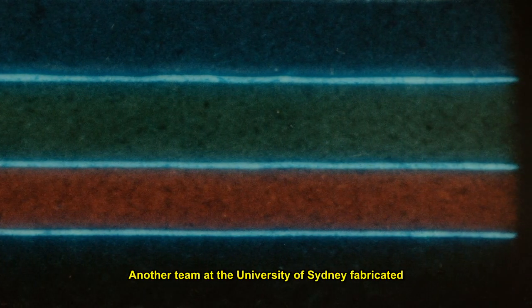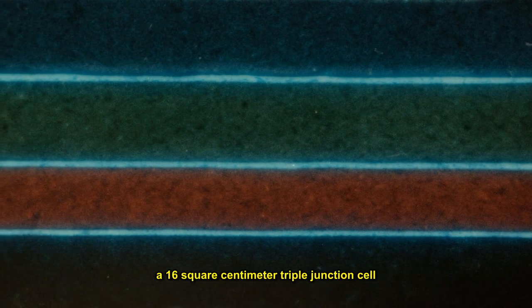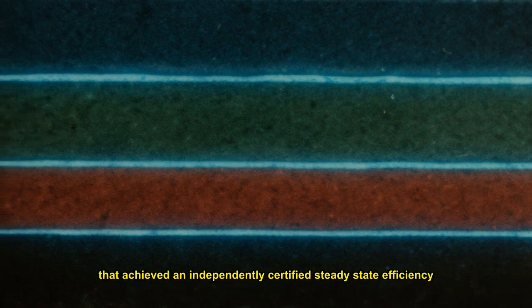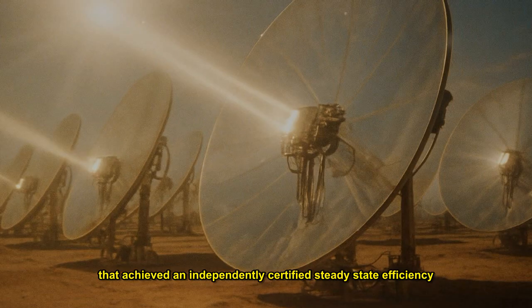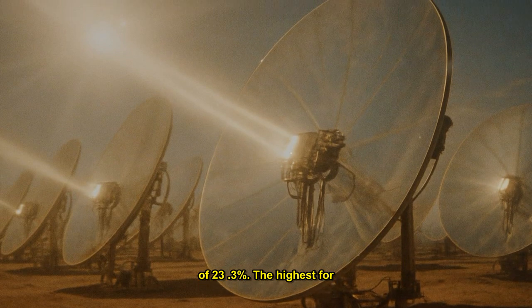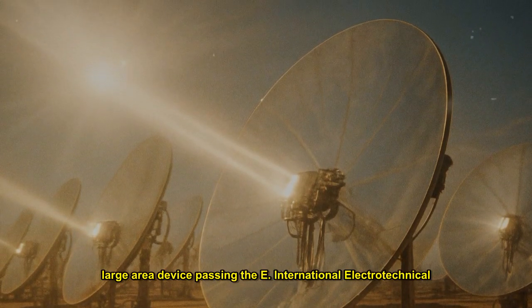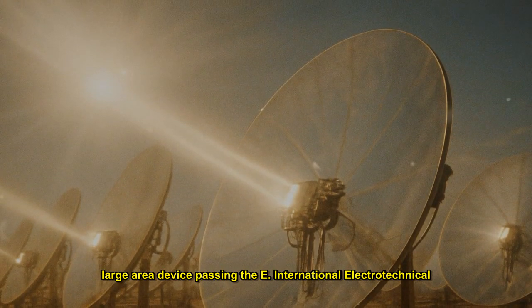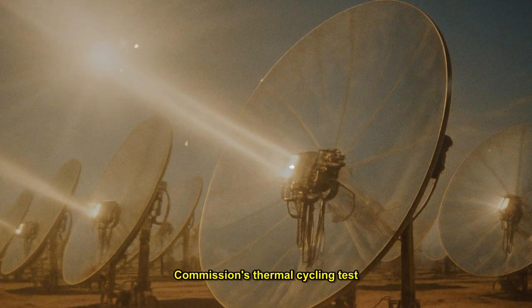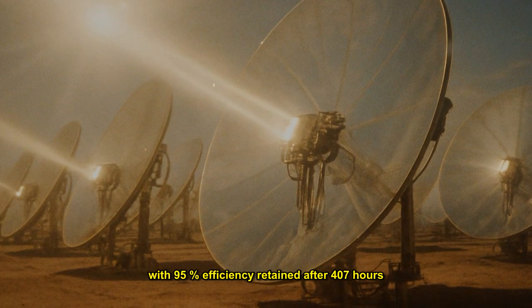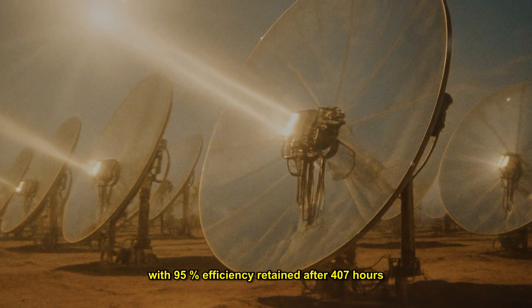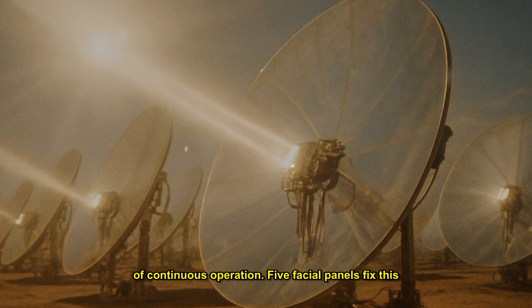Another team at the University of Sydney fabricated a 16 square centimeter triple junction cell that achieved an independently certified steady state efficiency of 23.3%, the highest for a large area device, passing the International Electrotechnical Commission's thermal cycling test with 95% efficiency retained after 407 hours of continuous operation.